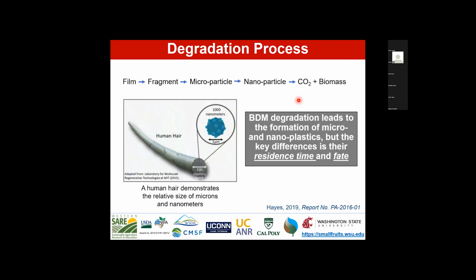So you might see the word micro and nanoparticles. Those are kind of buzzwords right now. We're very concerned about micro nanoplastics in our environment. And I do want to confirm that biodegradable plastics do form micro and nanoplastics, but the key thing to remember is the residence time. The residence time for these micro and nanoplastics of biodegradable plastic mulches are shorter, much shorter, and significantly shorter than polyethylene mulch because they are able to then be transformed into CO2 and biomass through biodegradation.